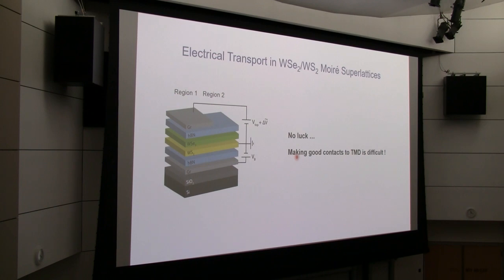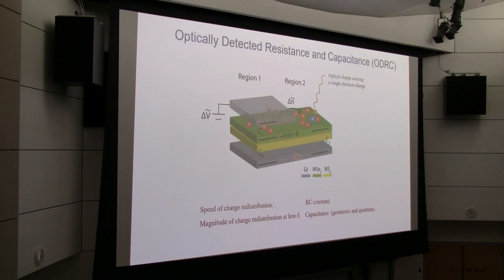And it took us quite some time trying to put contacts on the system and see whether we can indeed see a Mott insulator when you have one electron per lattice site. But it didn't work very well because for us it's extremely difficult to make a good electrical contact to the TMD. As a result, the transport is always dominated by contact rather than what's going on in the TMD material. So we thought very hard and used the optics tricks that Tony told us. We came up with a new idea: use optical detection to measure the electrical transport behavior.